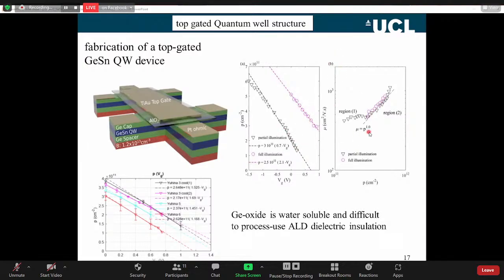We can also measure mobilities as a function of carrier density. So by changing the gate voltage, we change the carrier density. We tend to see two regions in these devices. Region 1 here, where not really much happens to the mobility. It's a constant mobility. Could be related to phonon scattering. We're not exactly sure. But in region 2 here, the mobility follows a power law. The hole density power is 1. Okay, it's linear. That is very characteristic of impurities in the quantum well, so-called background impurities. So we know we've got these background impurities in the quantum well that are causing the limiting mobility.